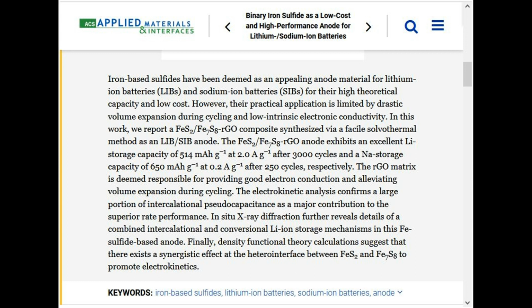In this work, we report a FeS2/Fe7S8 RGO composite synthesized via a facile solvothermal method as a LiB/SiB anode. The FeS2/Fe7S8 RGO anode exhibits an excellent Li storage capacity of 514 mAh/g at 2.0 A/g after 3000 cycles and a Na storage capacity of 650 mAh/g at 0.2 A/g after 250 cycles, respectively.